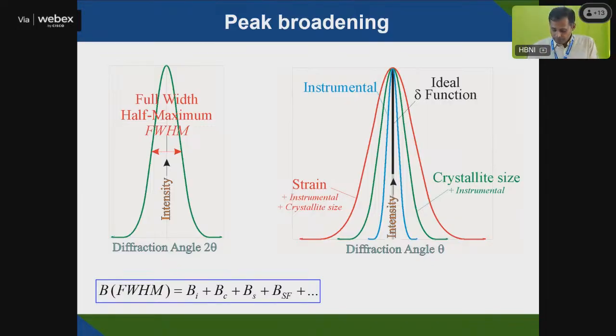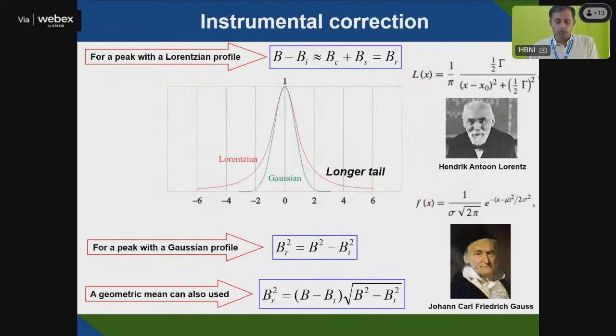So from the line broadening, if you separate out the instrumental broadening, you will be able to get the strain and crystallite size. Once you get an X-ray diffraction pattern, you fit it properly with either Gaussian or Lorentzian; you have to see which model fits best. If it is Gaussian, you take B squared minus BI squared, where BI is the instrumental line broadening. That means you take a silicon wafer and record its XRD pattern. Silicon generally gives a sharp peak at 28 degrees.